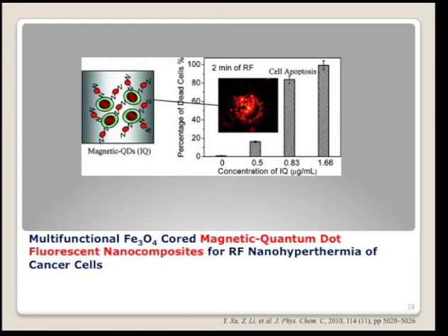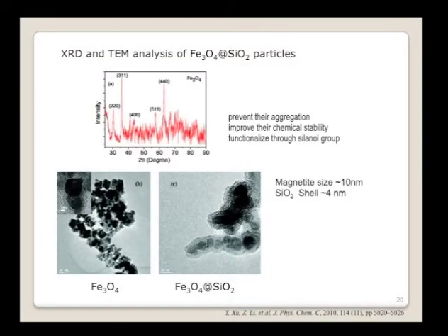First, we coated the iron oxide Fe3O4, we also call it magnetite, this kind of nanoparticle, with silica through the sol-gel process. We did XRD to check the crystal structure. This matches the magnetite very well. So we synthesized the magnetite nanoparticles.